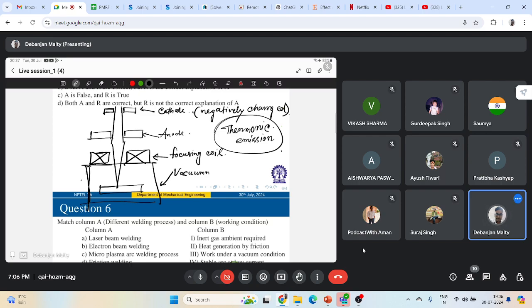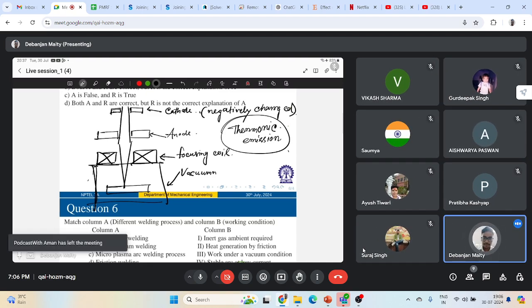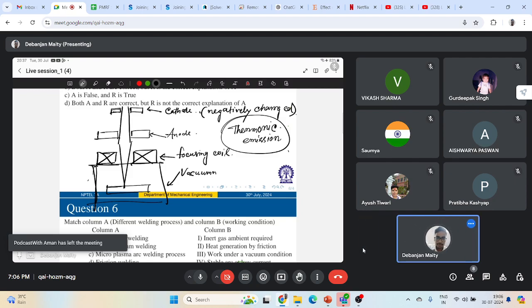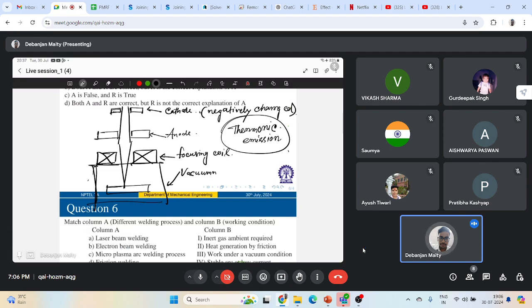So what is a typical current or typical voltage of an electron beam welding operation? At least the order of current and voltage. In electron beam welding, you will work in a milliampere range, right? It can have some 50 milliampere to 1000 milliampere, with some kilovolt order voltage, so some 50 to 150 kilovolt. So this is a typical range of electron beam welding operation.